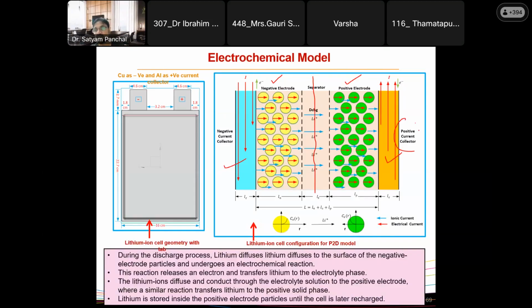So during discharge, current flows from positive to the negative, and lithium ions travel through the separator sheet from negative to positive, and electrons travel from negative to the positive electrode. During the discharge process, lithium diffuses to the surface of the negative electrode particle and undergoes an electrochemical reaction. This reaction typically releases an electron and transfers lithium to the electrolyte phase, and lithium diffuses and conducts through the electrolyte solution to the positive electrode, where a similar reaction transfers lithium to the positive solid phase. So the lithium is stored basically in the positive electrode particle until the cell is recharged at a later stage.